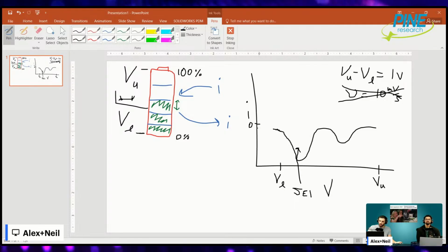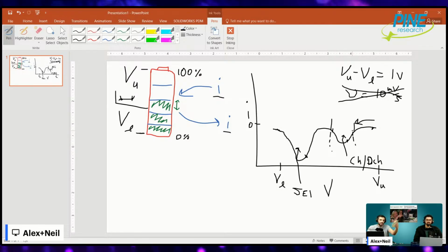And then the other thing is that look at the current. So if I'm scanning, for example, this direction, well, the current is low here. It's high here. It's back to low. It's high. I'm not charging or discharging my battery at a set rate at all, right? I'm not actually controlling the current in this case. I'm controlling the voltage. So that's a problem in and of itself, because if you consider, let's say this is the SEI and this is the charge discharge peak or a redox peak or whatever, the reality is that you've actually done most of your charging and discharging over this narrow range. And the current was changing. So it's like you're actually charging or discharging your battery at a very unstable rate.